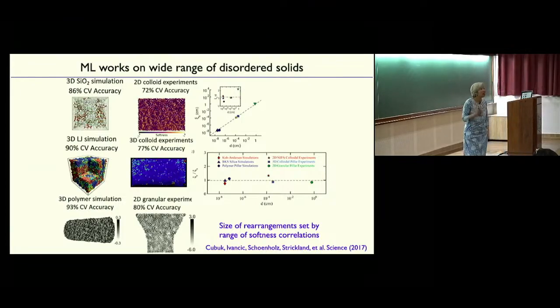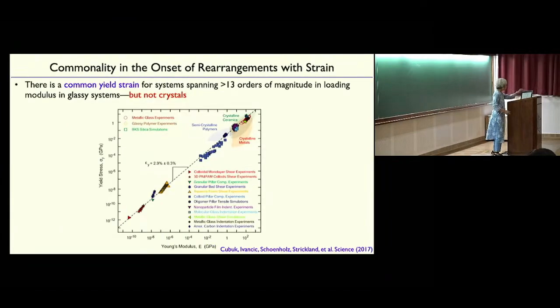So plasticity is correlated over very short scales. Those scales are set by the local structure, so even though these have very different potentials, all of these disordered systems are correlated over a very short length scale. All right, and here's the vertex model. The vertex model also falls on that. We did that later.